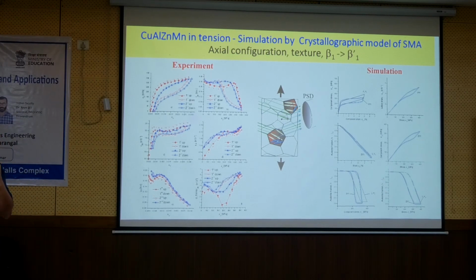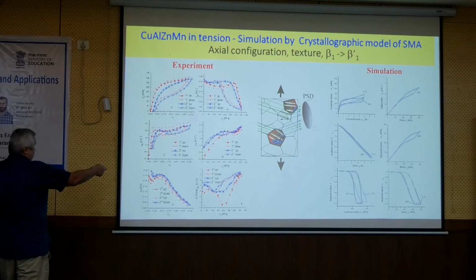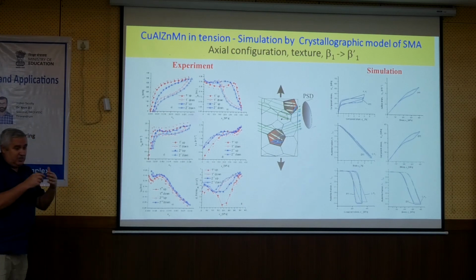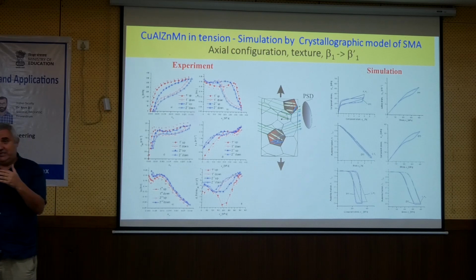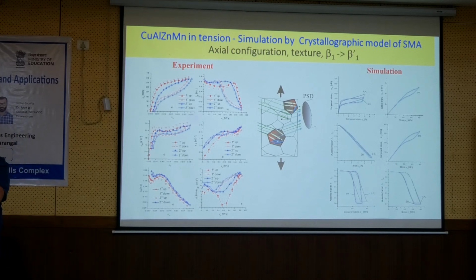So if you believe me in that, this is a very nice proof of that. This is a strain gauge which is in the material, and it tells you that it transforms when the internal stress is 20. And it's the same in the first, second, and fifth, and 100th cycle, because the phase transformation very nicely detects it.